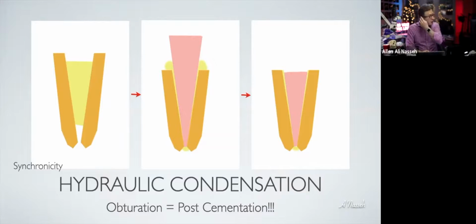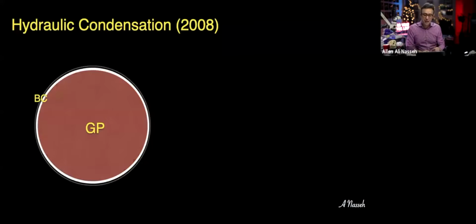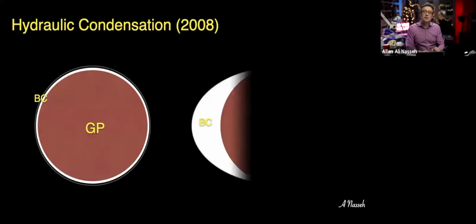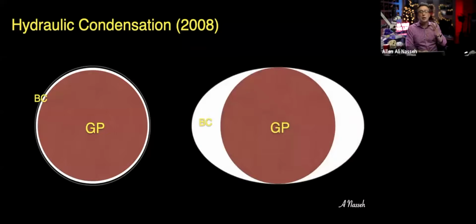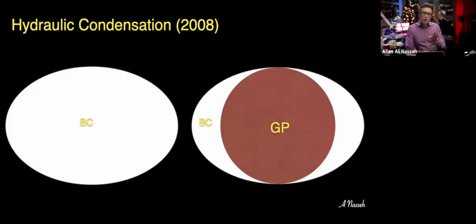It's called hydraulic condensation. It's not called single cone because you're not limited to use a single cone. You can use as many cones as needed if it's a big oval canal, and that's really the main thing to keep in mind. So if you have a round canal, you'll end up with gutta percha and just a little bit of sealer interface on the side. If you have an oval canal, you end up having a little bit more bioceramic on the sides. But the goal here is you don't want to fill the whole canal with the bioceramic,